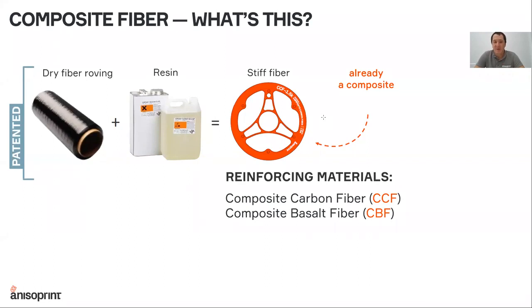So why is it called a composite fiber? It is not the raw material, it is not the dry fiber. As the first step of the technology that we do internally, and this is our patented process, we pre-impregnate dry fiber roving with a special resin to make sort of a pre-preg material, a preliminary impregnated material, and then we fully cure this material, and then we have the stiff, fully impregnated, very stiff fiber material, which we call composite fiber.